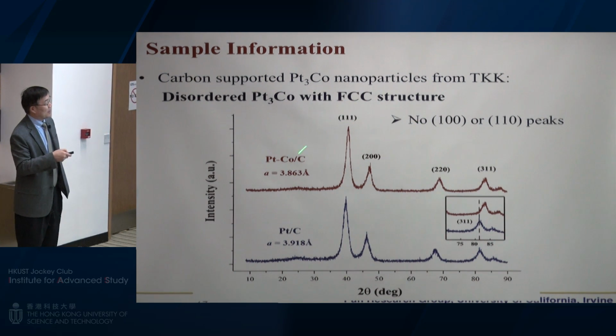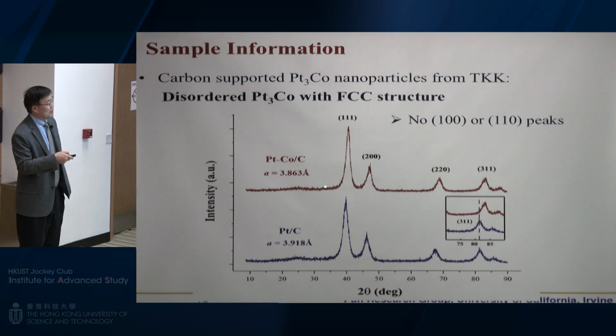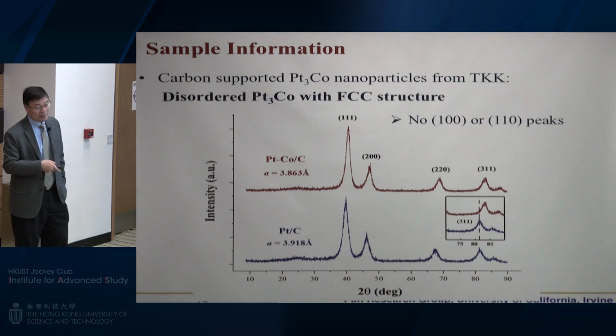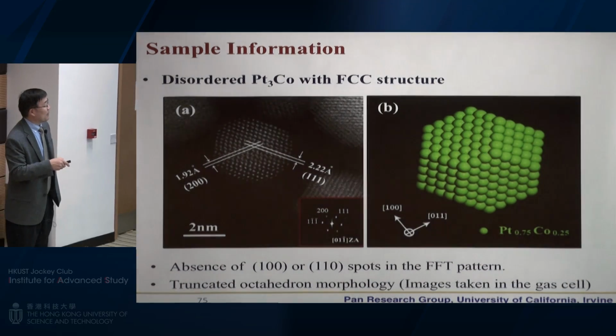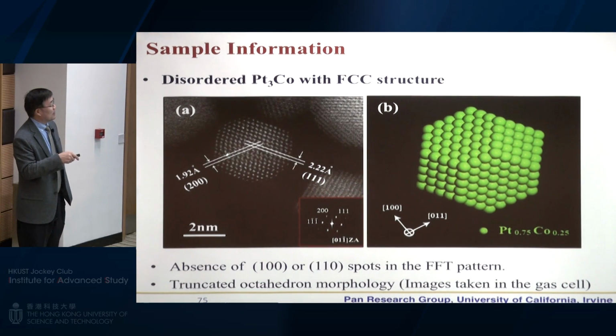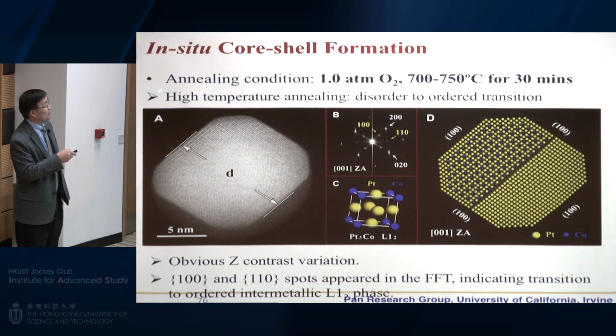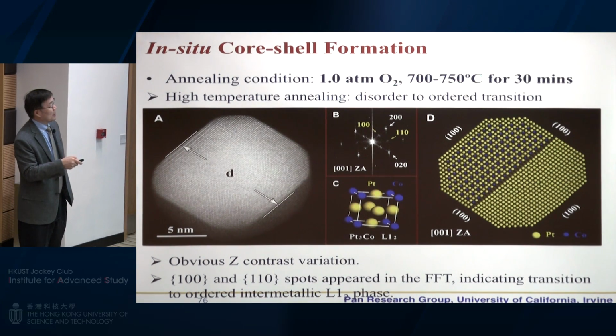By X-ray diffraction with in-situ experiment, we see that our material started disordered. There is no 100 or 110 peak. This means that the structure is disordered. Okay? This is in TEM. You can see that this confirms it is disordered. And if you put it in the TEM with 1 atmosphere oxygen pressure, then heat it to 700 to 750 degrees for 30 mins, you can see that the structure transforms to perfect ordered.